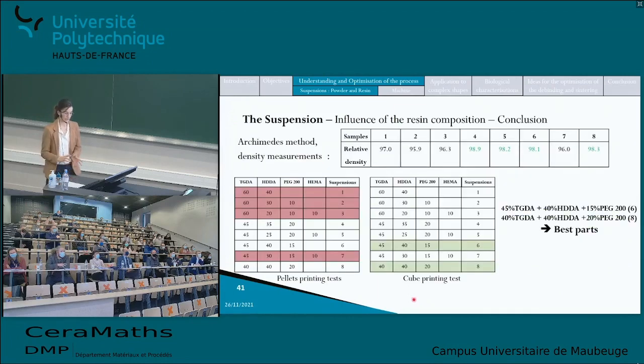So combining all of these results together, the density measurements, the microscopic measurement, and the SEM observation, it appeared that suspensions 6 and 8 were the ones providing the best parts with only a few defects and a high density. So these were the compositions that I selected to pursue the experiment, the optimum compositions to be printed with the powder I used.